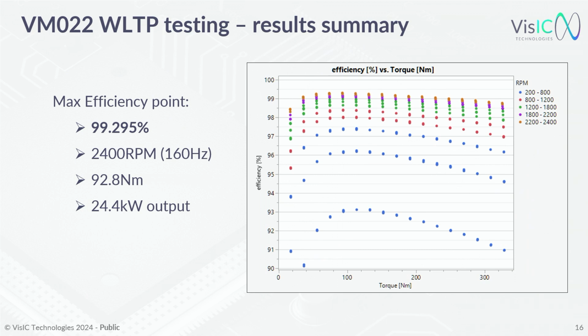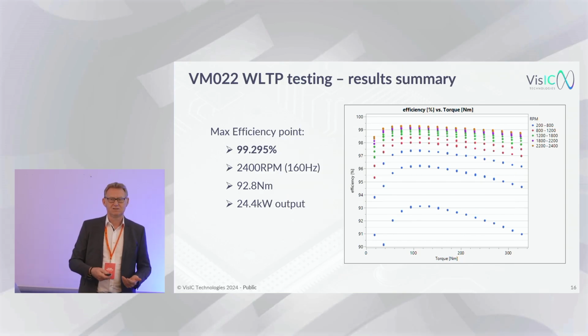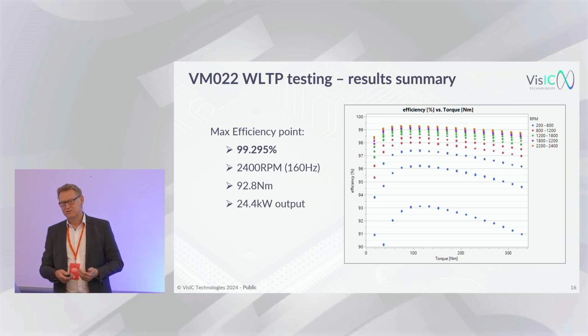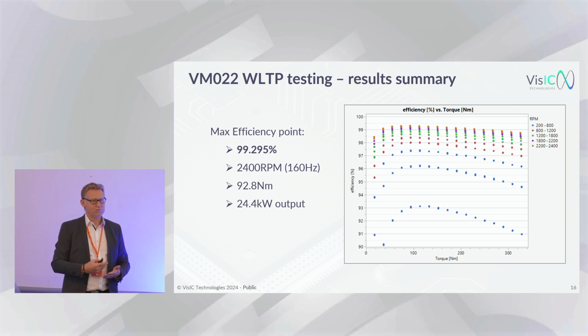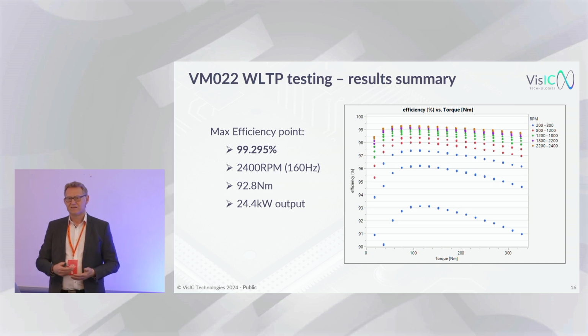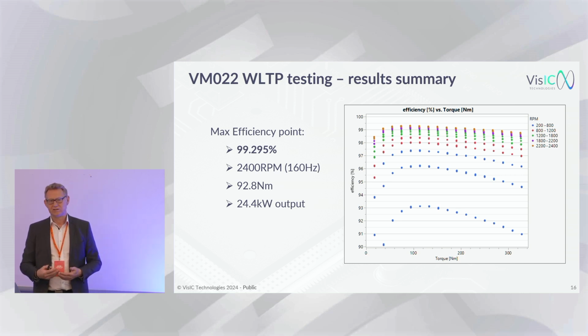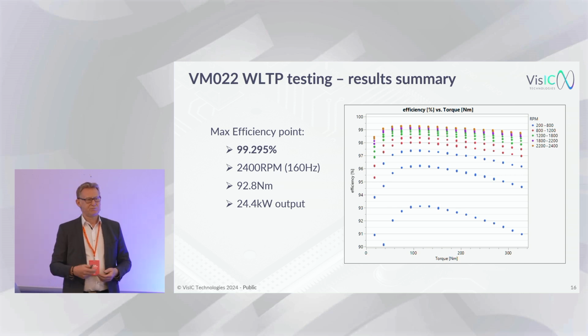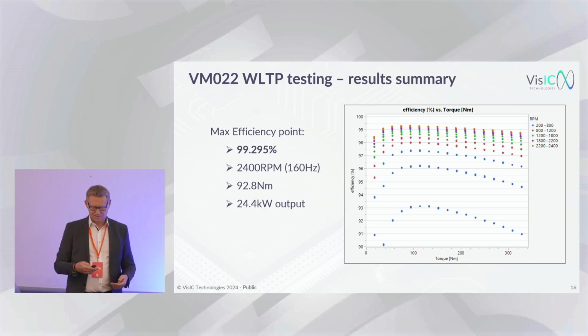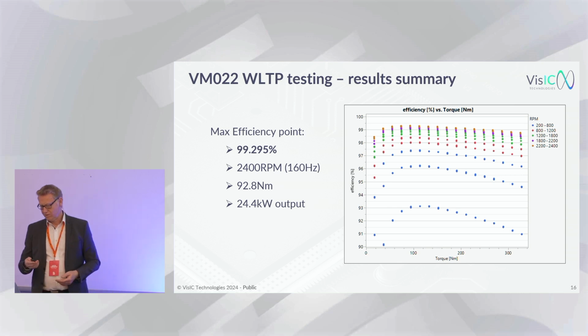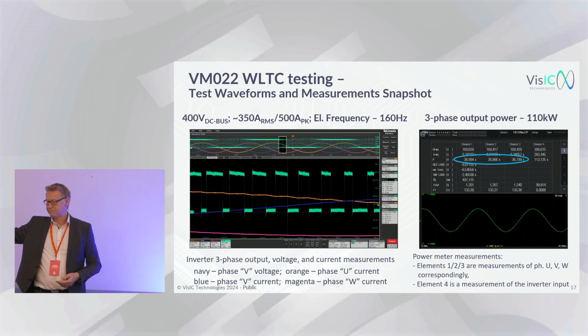And we achieved roughly the same efficiency as a silicon carbide inverter. Theoretically, you could even be better because you don't have a QRR, you don't have a body diode. So there's a lot of optimization still doable with this kind of setup. But it was a first test to show that yes, it's workable in the inverter environment. It can withstand the very high inductive load which you get as feedback to the gate, so that you're not destroying the devices. Under this condition, we were happy with the results that we can run this in this limited operation.